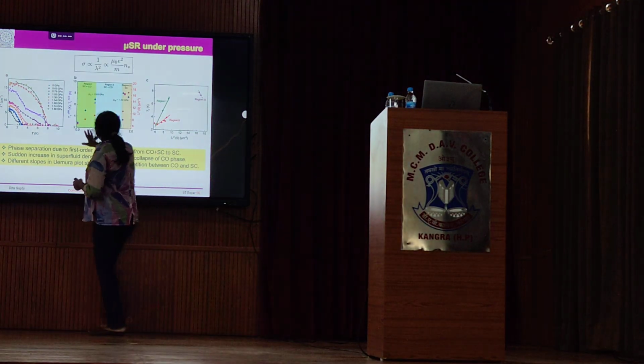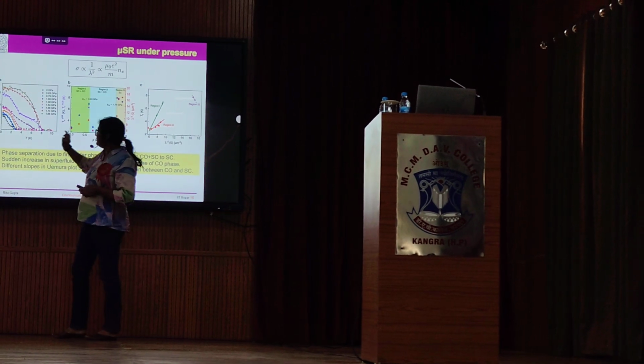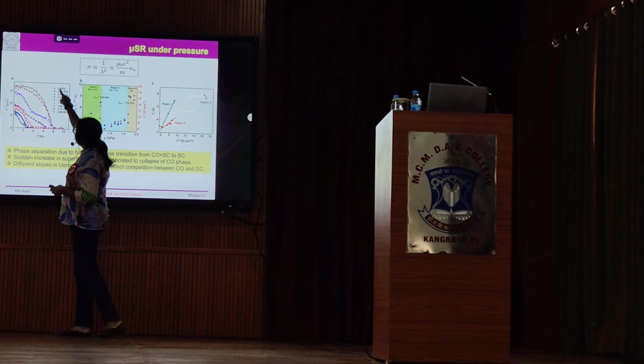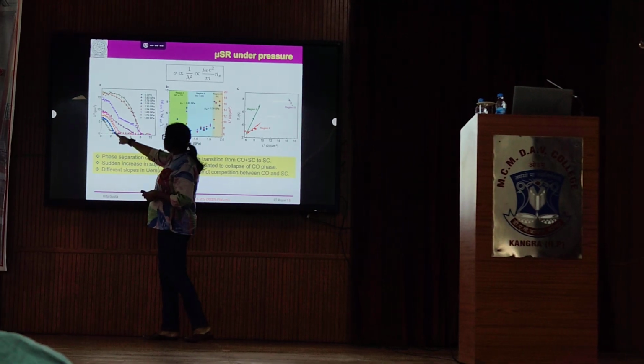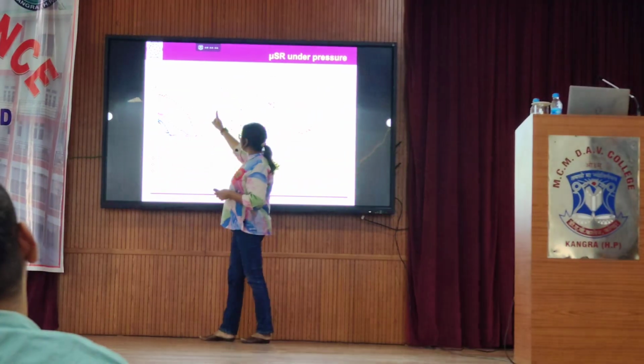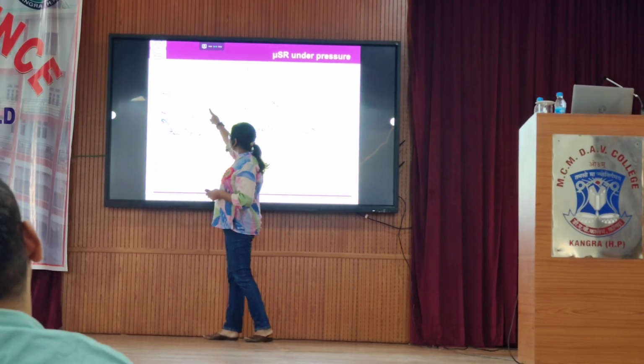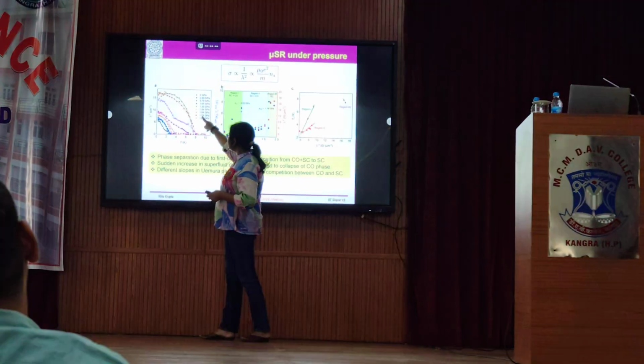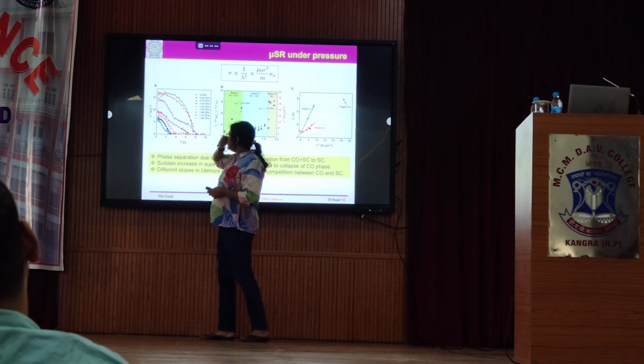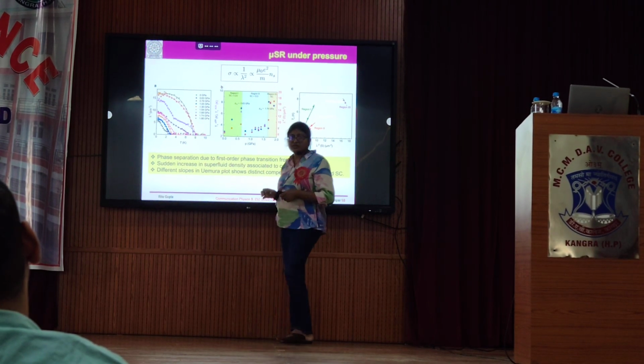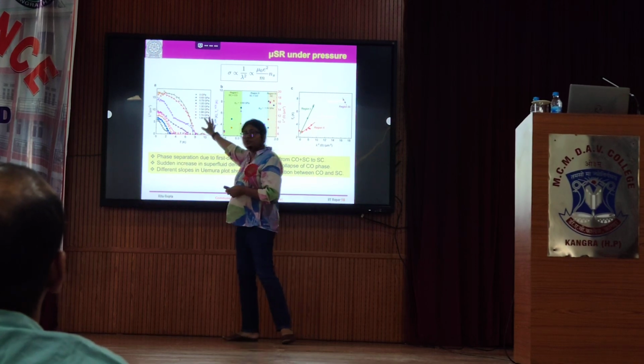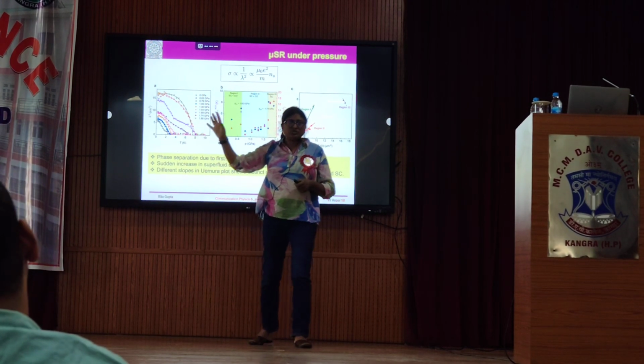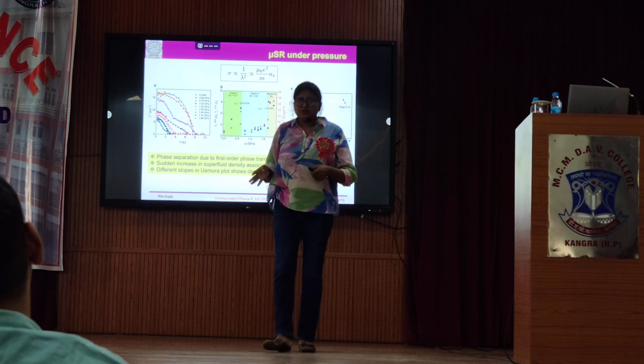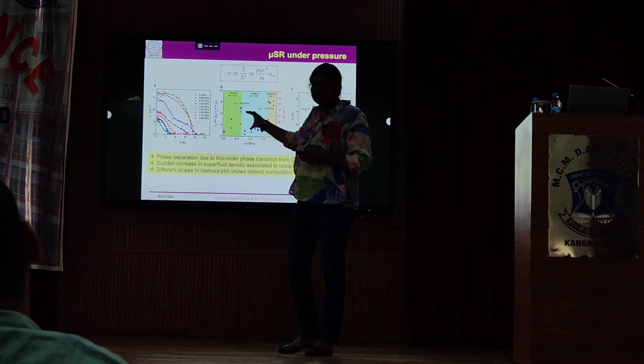So you can see, the high temperature experiment I am not showing here, but at 0 GPa, where GPa means the gigapascal pressure I am talking about, the TC was 2.5 K. But as soon as you keep increasing the pressure, what happens? At around 1.74 GPa, your TC suddenly goes from 2.5 to 8 Kelvin. So it is almost a threefold increase in TC. Okay, and what happens exactly at this pressure?